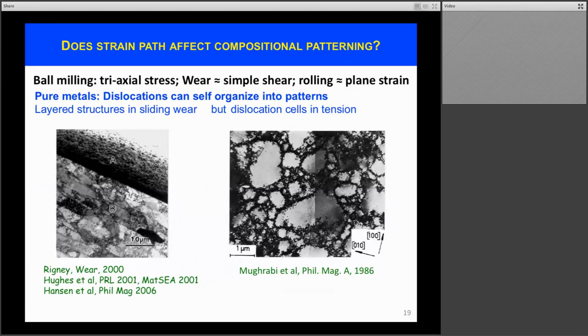So here we talked about self-organization so far of alloys. There is another complication to this picture, which is that when we plastically deform materials, depending upon the conditions we impose, we'll have different types of strain path or stress conditions. Ball milling typically, for instance, generates triaxial stresses. Wear generates, or can be approximated by, simple shear deformation, rolling with plane strain. And it is known that in response to this plastic deformation, pure metals may self-organize as a result of self-organization of dislocations. So here you see on the left an example of layered structures that formed in pure copper during sliding wear, but dislocation cells and subgrains forming in tension.